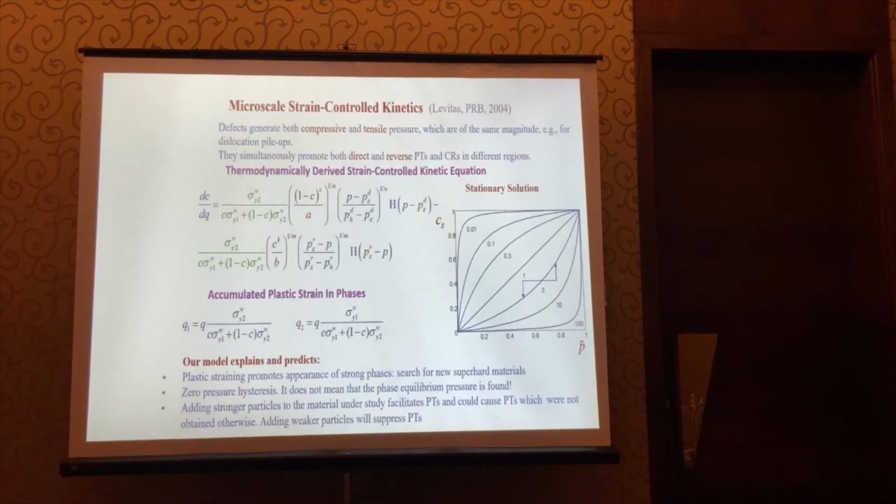But right now in our finite element simulations, we still use our old theory, which still takes into account all that we learned at the nanoscale. And in particular, defects generate both compressive and tensile stresses. That is why they promote both direct phase transition and reverse phase transition. We have two terms. Nucleation is barrierless. Time is not a parameter.